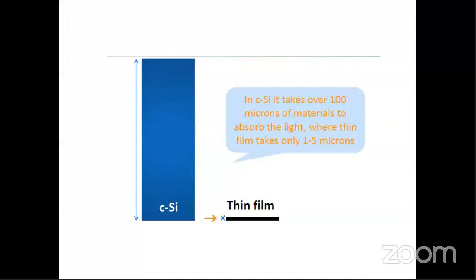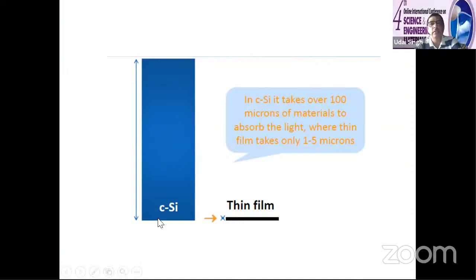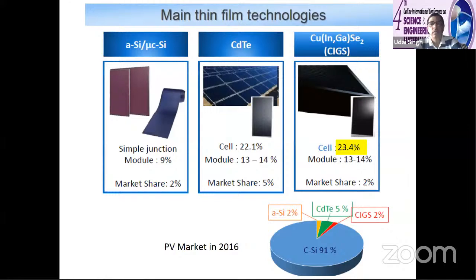As I told earlier, the crystalline silicon thickness is too much, but thin film you can prepare within 1 to 5 micron. I will focus on copper indium gallium diselenide, whose lab scale efficiency has reached around 23.4%, comparable to silicon. Regular module production efficiency is 13 to 14%, sometimes going to 16 or 17%. But the market share is still only around 2 to 3%. Not much has changed.